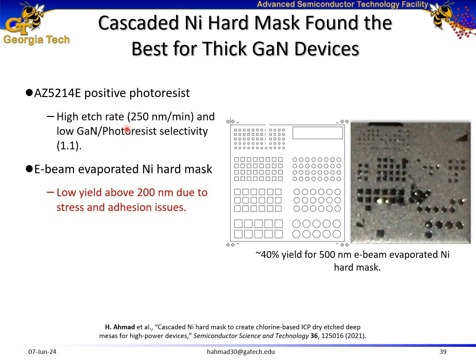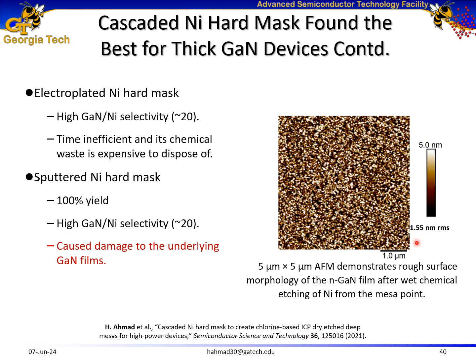The first one is positive photoresist, but I found its gallium nitride to mask selectivity to be very low, not suitable for our case. Then I studied E-beam evaporated nickel hard mask, but its yield was approximately 40%, once again not suitable for our study. Later, I performed a study on electroplated nickel hard mask. Its selectivity was high, but it is time inefficient and also its chemical waste is expensive to dispose of. Later, I studied sputtered nickel hard mask. Its yield was 100% and its selectivity was high, but it caused damage to the underlying gallium nitride films.